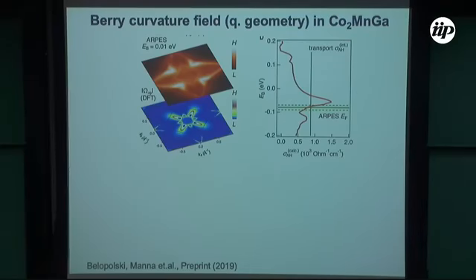When we do that, based on ARPES, we predict that this compound, if someone does a transport measurement, should have an anomalous Hall conductivity on the order of 10 to the 3, a little less than 10 to the 3 standard units. So in other words, it's here. And there's a near divergence here, because then you hit some Weyl point. Weyl points are singularities of the Berry curvature field, right? So we see that we are below the Weyl point, so you should not hit the singularity. So based on spectroscopy, we predict that the transport should have a value in that order.